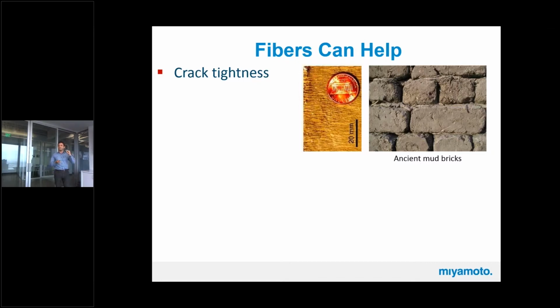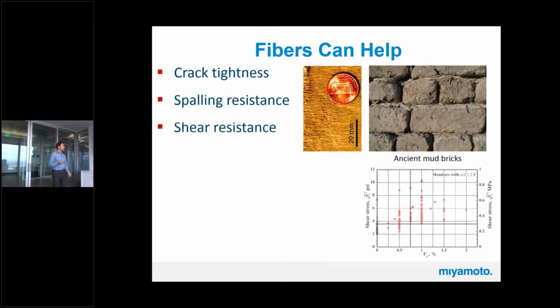So if you have fewer cracks with limited width, you enhance the service performance of the structure. Additionally, it holds the structure and concrete together and provides a kind of self-confinement effect, and prevents spalling in the concrete. This one is one of the main characteristics of fibers: it increases the shear strength of concrete. Here you can see that by using 1% fiber in the concrete, you can easily double or triple the shear strength of concrete, which is huge.